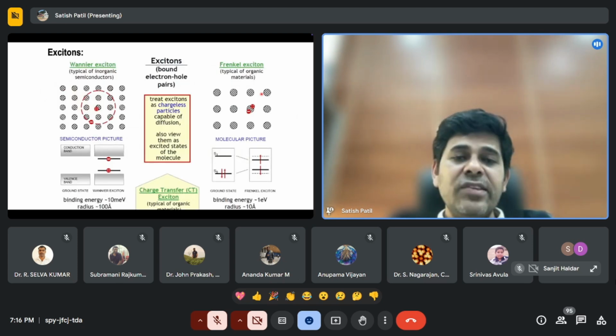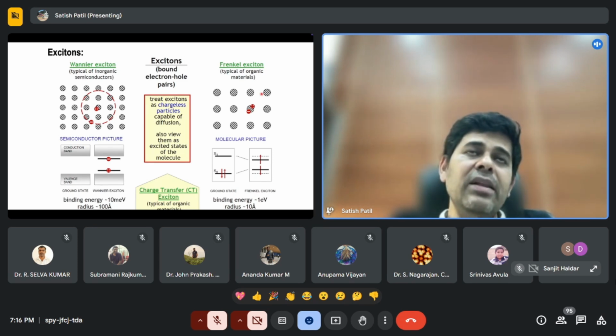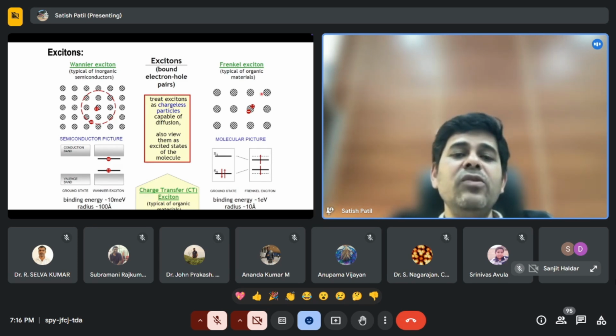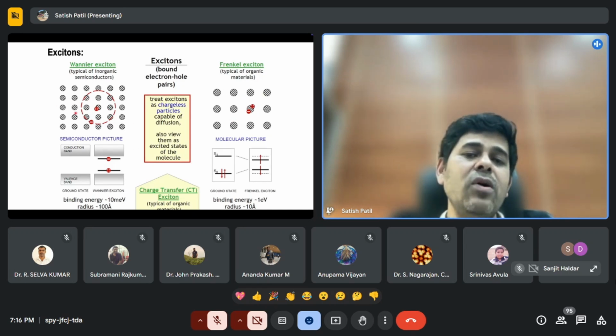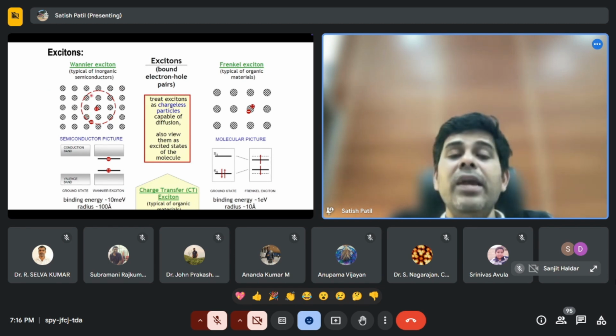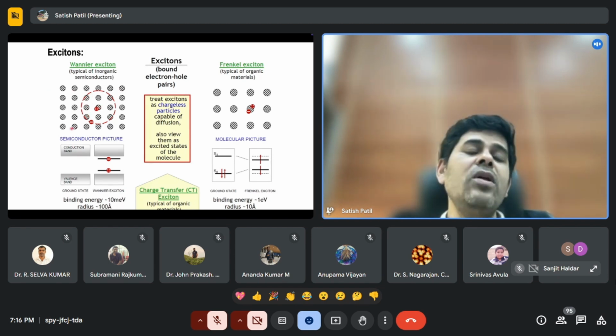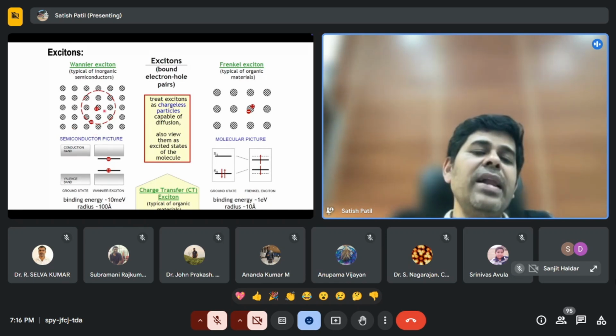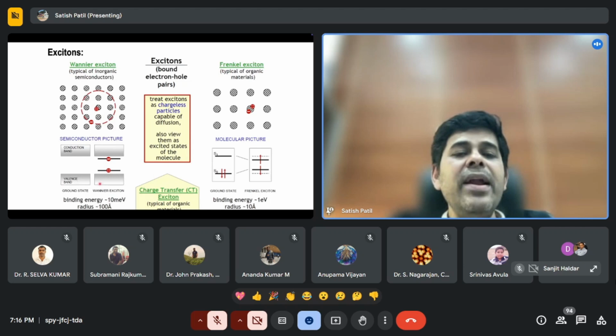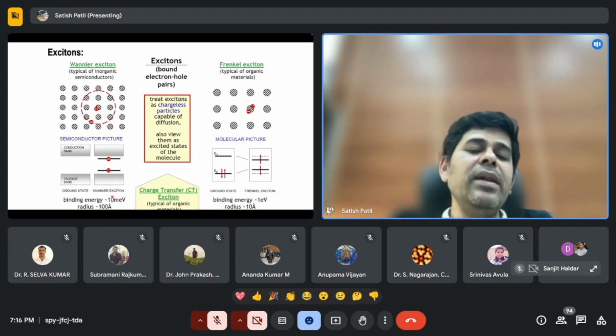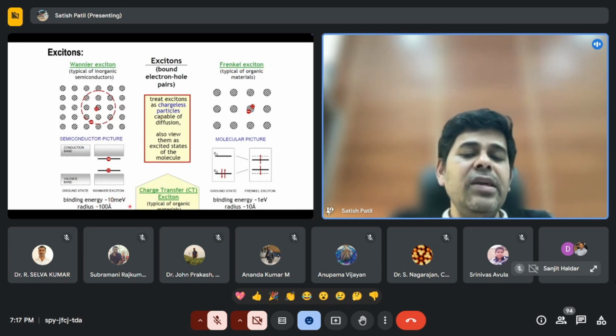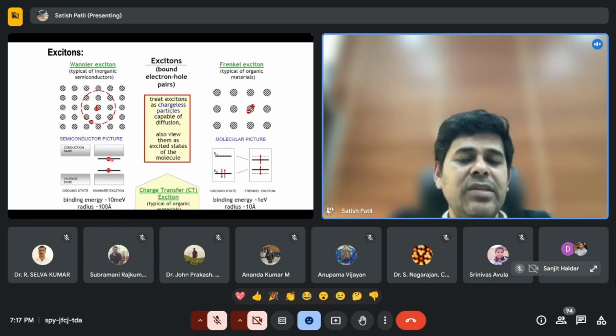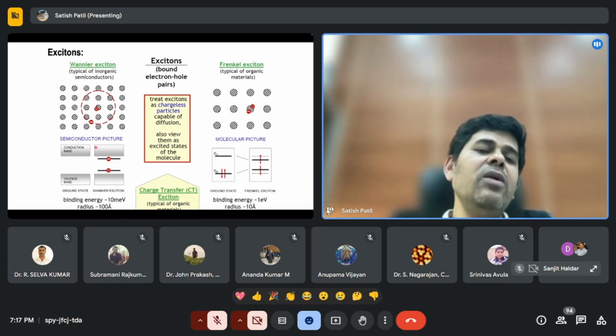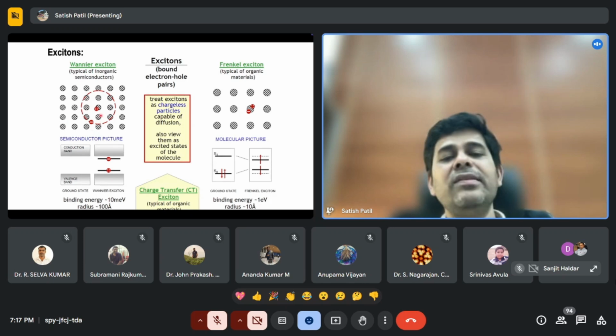A little bit more on excitons. This is very basic fundamentals of organic semiconductors that you should know. This is a Mott-Wannier exciton. You see that this is a conventional three-dimensional inorganic semiconductor where you have hole and electron. They are delocalized, not localized on one lattice site. Soon after you shine the light, you generate a free hole and electron, and the binding energy of this hole and electron is 10 millielectron volt, and the room temperature energy is 27 millielectron volt. So the room temperature energy is sufficient to separate hole and electron. That's the reason you make very good solar cells using an inorganic semiconductor like silicon.